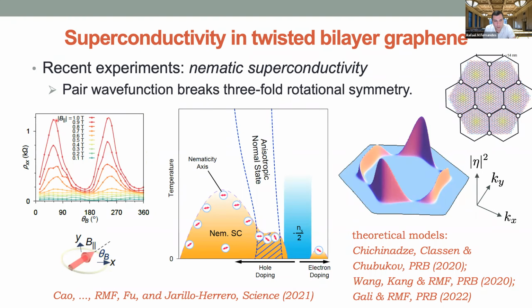The fact that this twofold anisotropy axis rotates is a strong indication that this is a spontaneous nematic superconducting phase, meaning that the nematic gap function, as I'm schematically plotting here, breaks the threefold rotational symmetry into 2. There have been different models, different ideas to try to explain that.